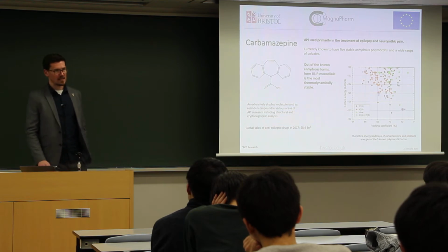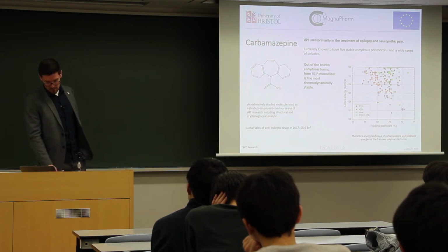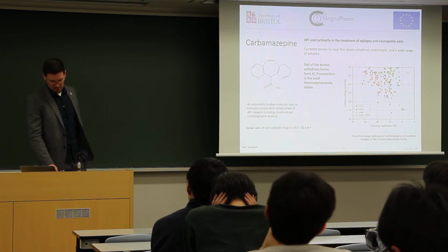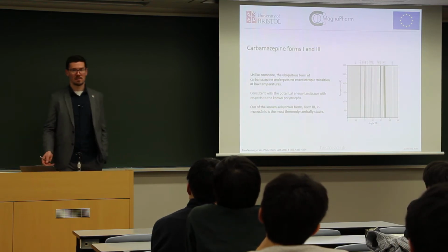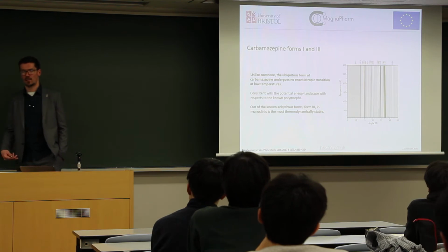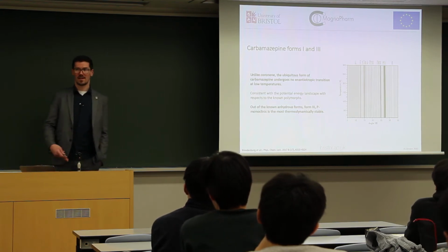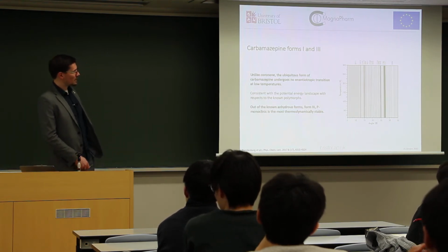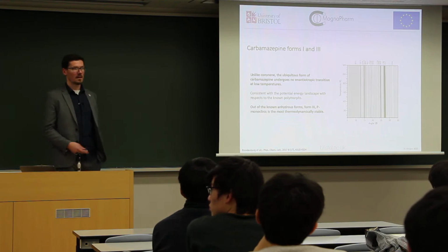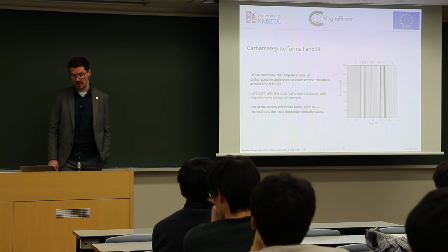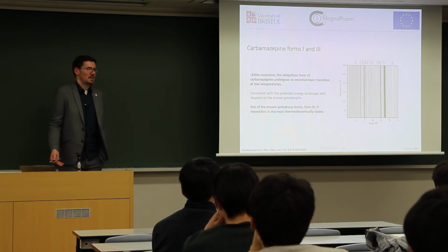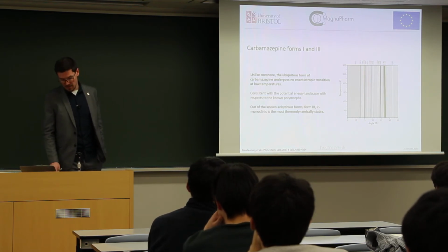Why no one's seen it yet, I mean, it makes sense, but I'm not going to go into that here. Anyway, so I did the low temperature powder diffraction on it, again, to see if there was any kind of phase transition from one to the other. And what I see is nothing. There's just expansion, contraction, that's it, no phase transition whatsoever. So am I to expect anything to change with carbamazepine?